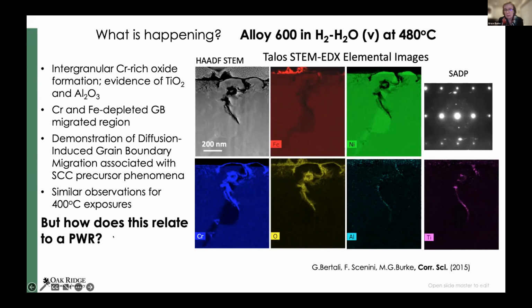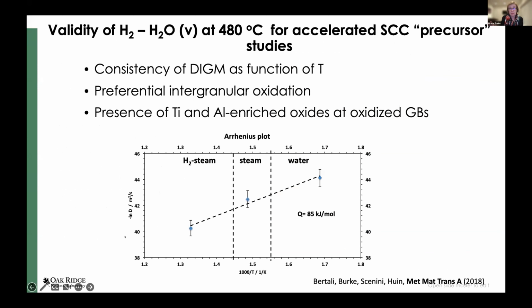So we can see this at various temperatures, but hey, is it relevant to a light water reactor? Well, we looked at the hydrogenated steam, we looked at steam, and we looked at water exposures, and we're assessing the extent and the consistency of DIGM as a function of temperature. And well, it's only 3 points. However, you can draw a line through them. And that means we can get a slope, which tells us that the mechanism is consistent across that temperature range. So it really actually is relevant.